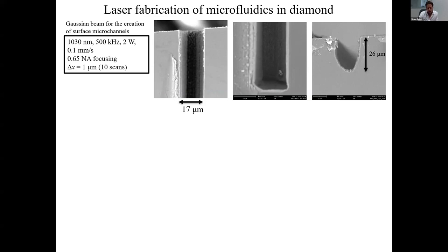Now, as of yet, we've been unable to fabricate buried microfluidic channels in diamond. People have demonstrated this in glasses using the post-etching technique. But what we wanted to first show was surface microfluidics. And in fact, we showed very, very nice channels using these very standard focusing conditions here. And so we're quite pleased with the aspect ratio.